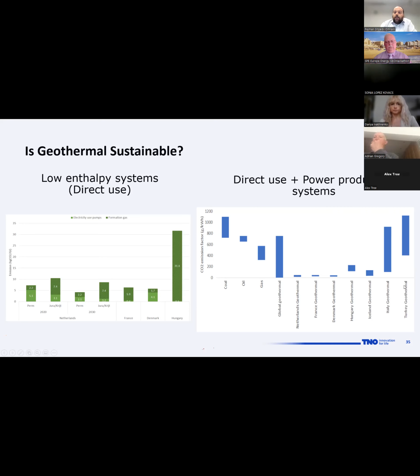geothermal systems. And if you look at a bigger perspective, where you also bring in the geothermal power production sites and compare them with coal, oil, and gas, you see that the emissions of the low enthalpy geothermal systems are pretty low compared to oil and gas systems. There are still some geothermal plants in the world where the emission factor might look high, but there is also quite a high share of natural gas and CO2 being produced from these wells, so please take this with a pinch of salt. If you normalize it based on the energy content that you're producing, these values would also be much lower. So compared to what we get from the fossil sources, yes, it is a sustainable source.